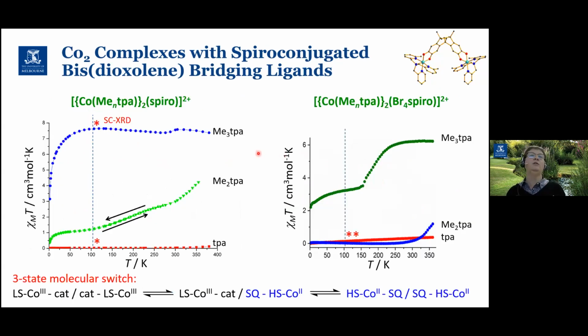So I'll just take you through some of the results there. First of all, on the left here, we have the Spiro complex. This is the susceptibility data. In that version where we have the plain TPA ancillary ligand, just like in that monomer from the Florence group, that's temperature invariant diamagnetic. So that dimer is actually stuck in the low spin cobalt-3 catechol form on both halves of the dimer. And again, crystallography at 100 Kelvin, the bond lengths are entirely consistent with that.